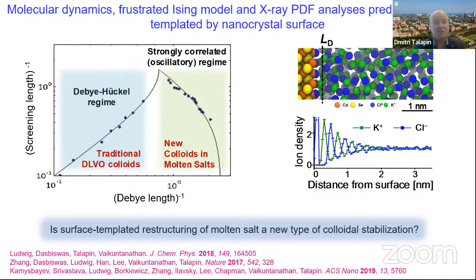And you have a transient layering of cations and anions next to the surface, which we can see in a frustrated Ising model analysis or in molecular dynamics simulations. What is most important, we can also see this effect in hard X-ray pair distribution function analysis studies. So it looks like this surface-templated restructuring of molten salts is emerging as a new type of colloidal stabilization, and that's work in progress.